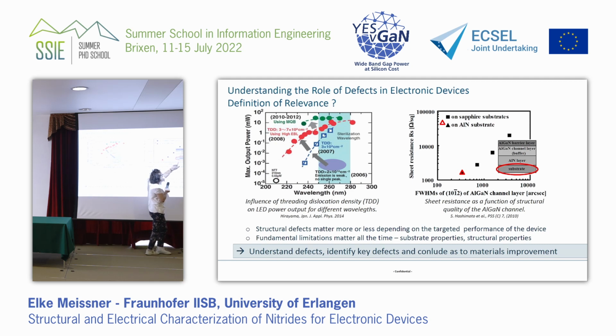But this only works if we use an aluminum nitride substrate: an aluminum nitride substrate, underneath an aluminum nitride layer, underneath the AlGaN channel, underneath the AlGaN barrier. If we put this all on sapphire, for example, then the number of dislocations is higher and the sheet resistance is far off what we want, by orders of magnitude. So this is how the substrate determines it. But if you can live with it and say it's fine for what you want to achieve, then you don't need to bother further. Fundamental limits matter all the time, but everything else is also a matter of definition.